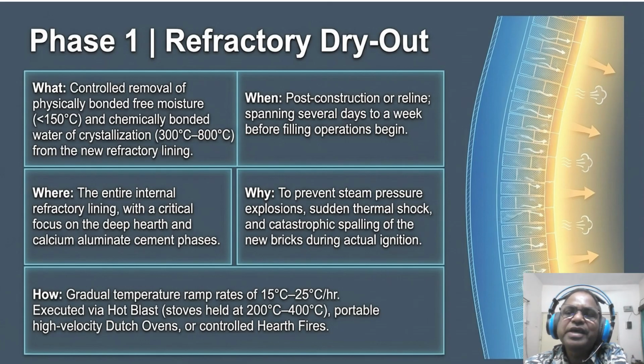So why such a slow pace? If we move too fast, the internal steam pressure exceeds the tensile strength of the refractory, leading to spalling, or effectively the brick exploding from the inside out. So the dry out stage is really very important, and a failure here is a death sentence for the hearth. We must ensure the calcium aluminate cement phases are fully cured before the first coke charge ever touches the floor.